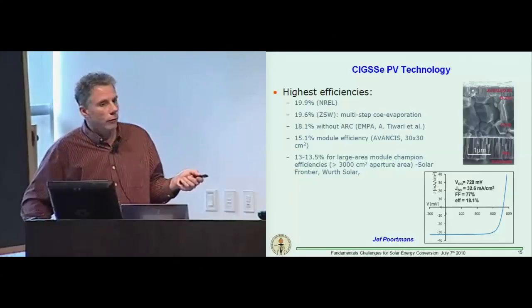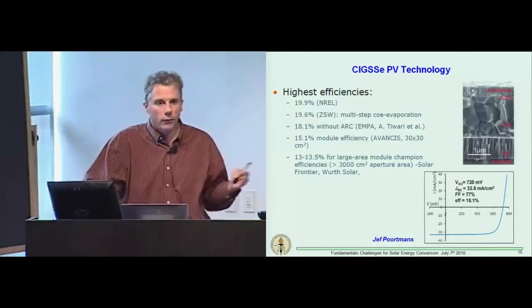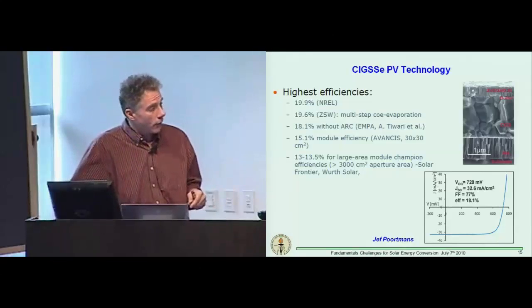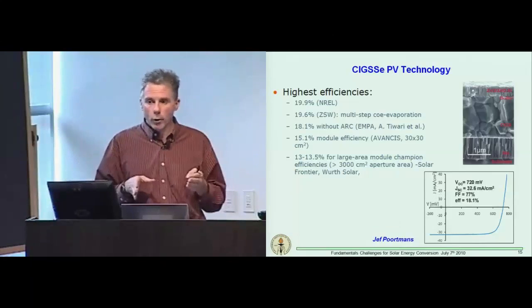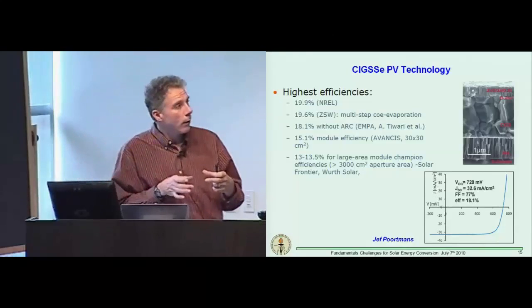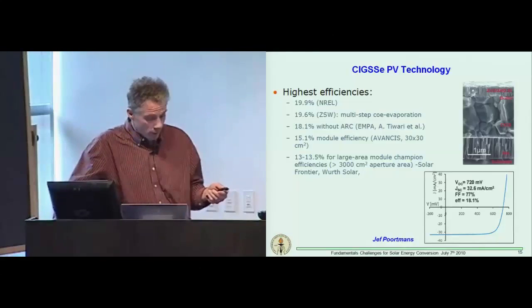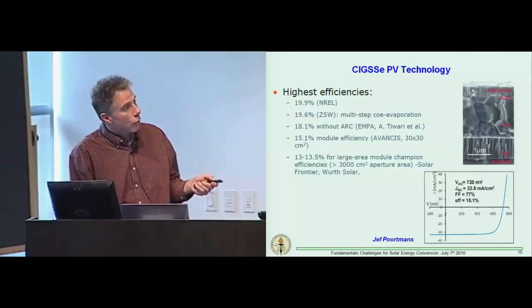module-like arrays. And so as a result, for example, companies like NanoSolar, which originally championed the notion of depositing CIGS films on large area web-like substrates and making essentially a module level cell structure, have chosen instead to enjoy the efficiency benefits of segmenting their foil into cell-like coupons and then binning them, similar to the practice that's done with wafer-based photovoltaic devices, which are then assembled in modules in a conventional stringing process. So making materials that are uniform over large areas is a challenge for truly thin film photovoltaics technologies.